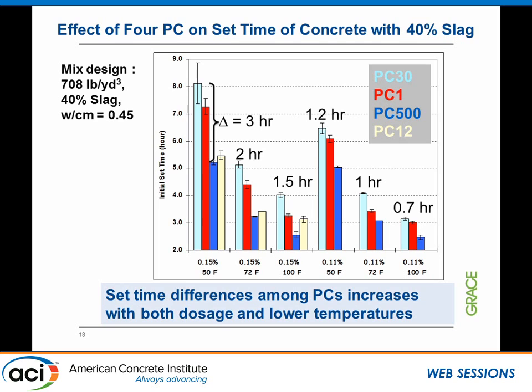So in this case, what we're showing is that there are differences among the polycarboxylates, where at the lowest temperature and the highest dosage, you see the biggest difference. So in here, the cold temperature gave you about a 3-hour difference, and the hottest temperature gave you about 1.5. And in terms of dosage, this is a 3-hour versus 1.2. So we realize there are differences between the chemical response to the dosage and to the different temperature regime.